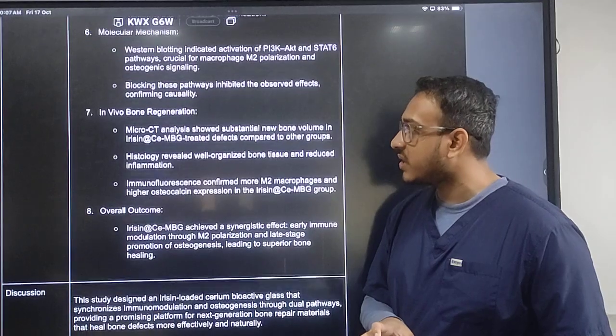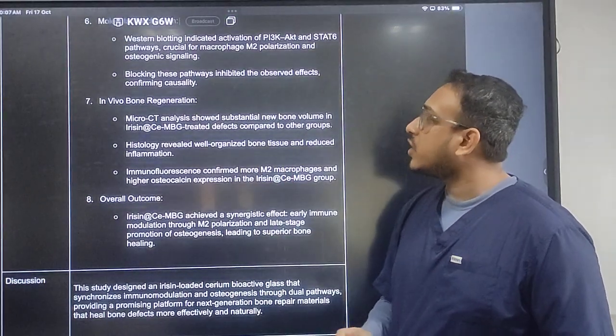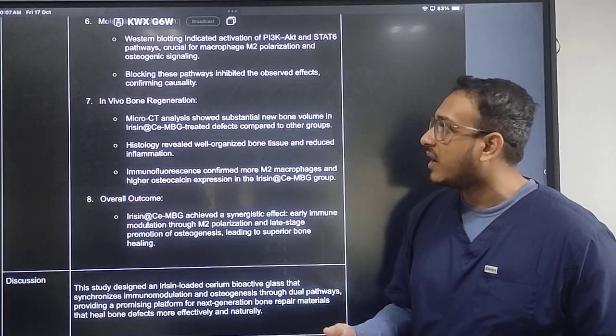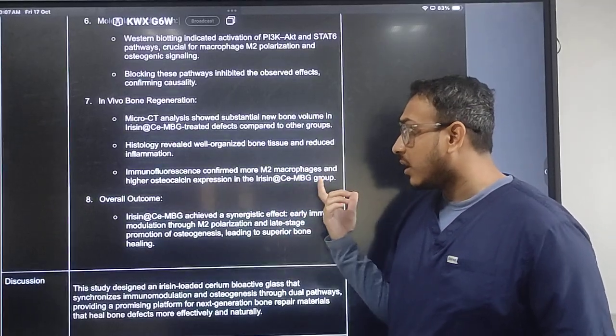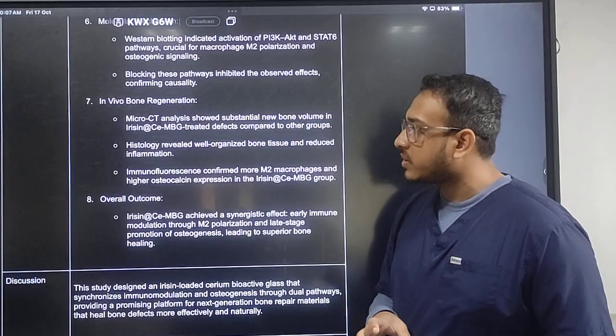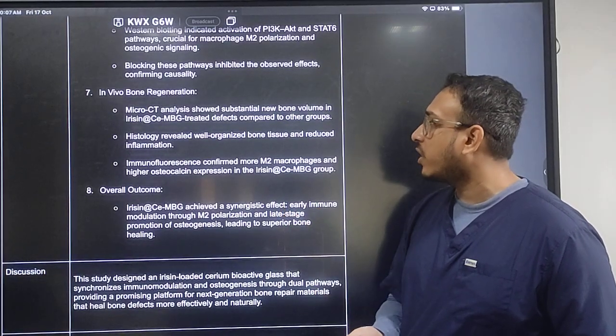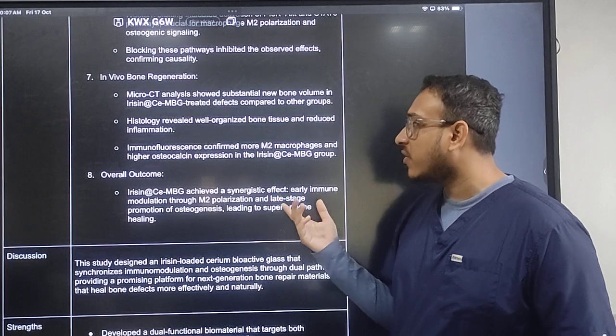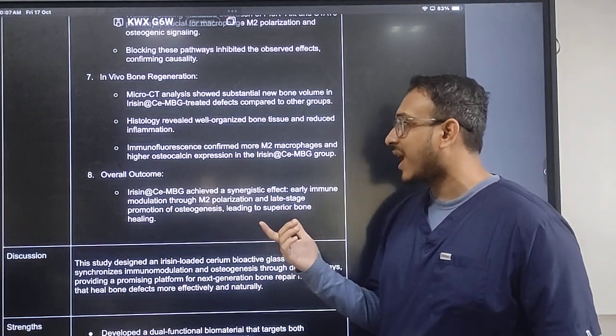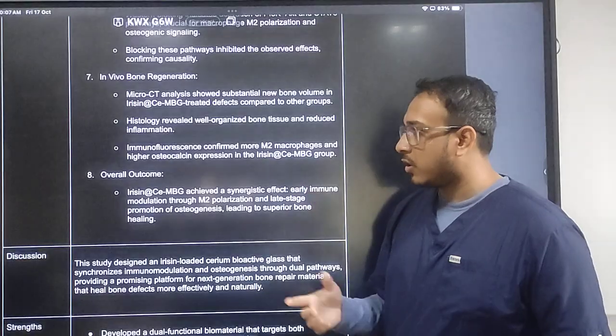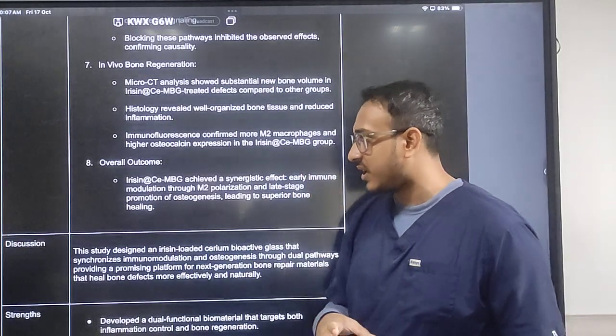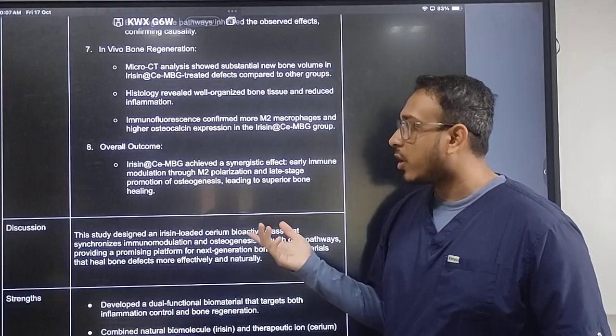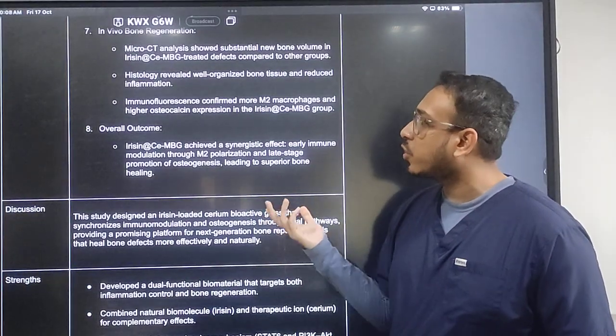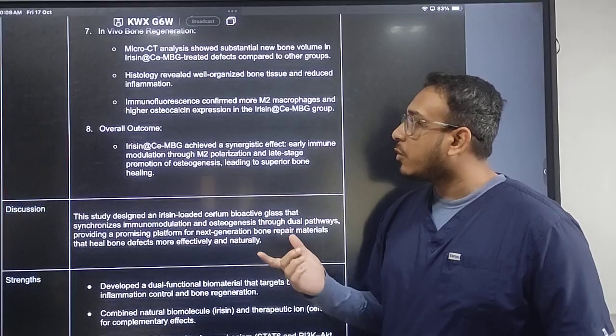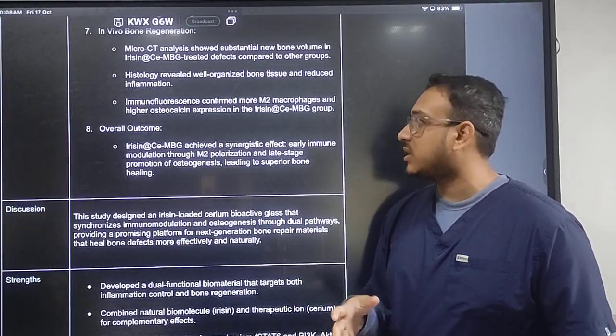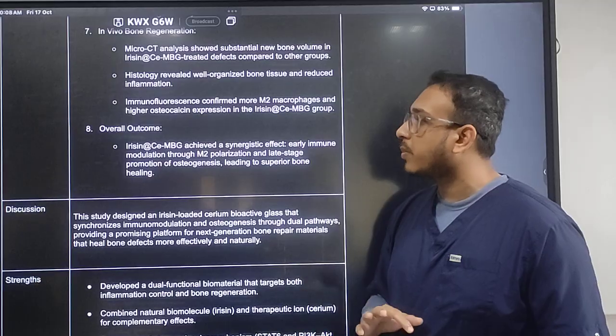For in vivo bone regeneration, the micro-CT which they did showed substantial new bone volume in the material-treated defects compared to the other groups. The histology revealed well organized bone tissues and reduced inflammation. Immunofluorescence confirmed more M2 macrophages and higher osteocalcin expression in the group with the material injected. Overall, the material showed a synergistic effect: early immune modulation through M2 polarization and late stage promotion of osteogenesis, leading to superior bone healing.